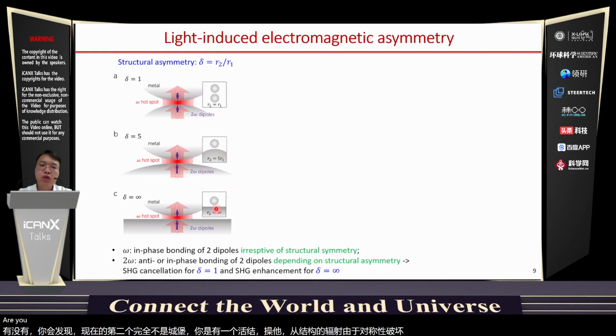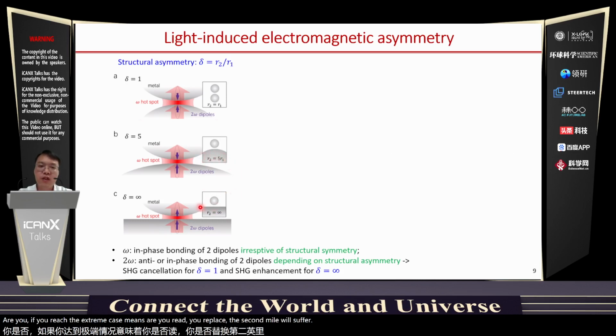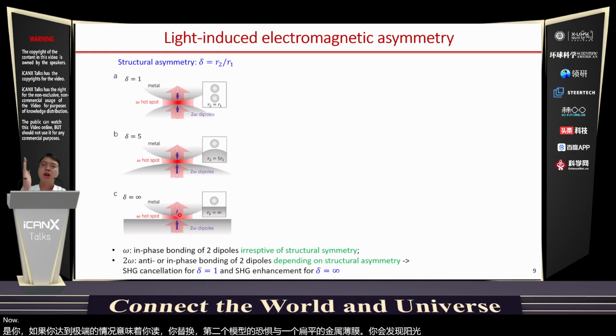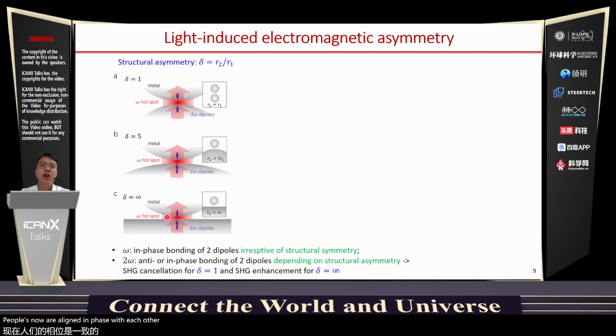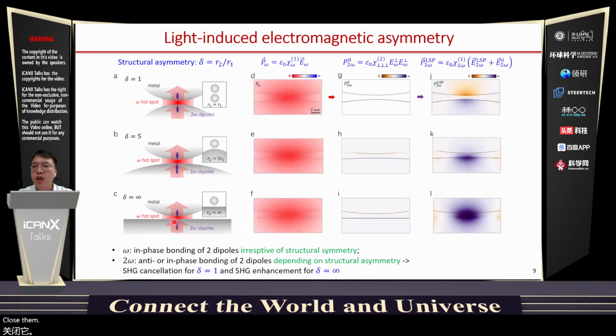And if you reach the extreme case, which means that you replace the second nanosphere with a flat metal film, you will find that the second harmonic dipoles are now aligned in phase with each other. So this means that we can get a very, very efficient second harmonic generation. Actually, this symmetry breaking concept has been verified in our analytical calculations.